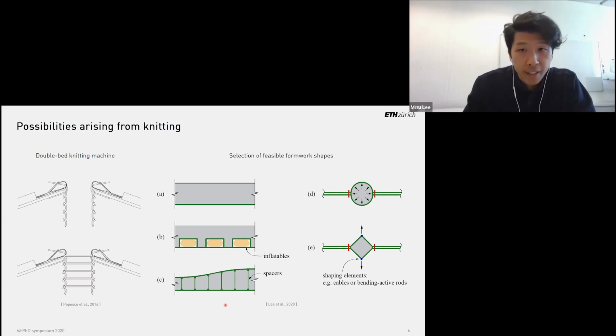Here, if you connect two layers of textile along two linear paths, a channel is created, which can be inflated by concrete pressure from the inside to create this circular cross-section. And then furthermore, shaping elements such as cables or bending active rods could be used to define the vertices of a cross-section with partially straight surfaces, as shown here.